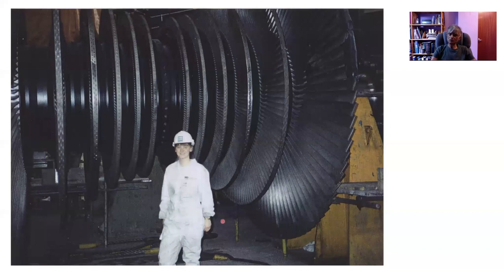So this is Tracy Cool, who was my PhD student many years ago. And she's, if my memory serves me correct, about 5 feet 10 inches tall. So you can imagine the size of the steam turbine, which also extends in this direction towards the left. It's huge, okay? And there is no possibility of obtaining, for example, the shaft by rapid quenching and still having a chemistry which is suitable for all the other properties required, for example, the creep resistance and so forth. So these components in power plant are often bainitic in structure.